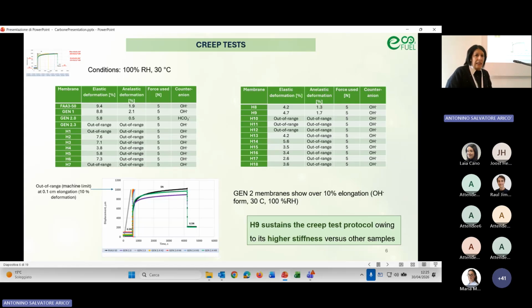The first test in terms of mechanical test was a creep test in the elongation mode. We used the standard protocol that we have set at CNR that consists in stretching the membrane at 0.5 Newton, then a sudden increase to 5 Newton for 1 hour, and again returning to 0.5, and this was set up for the benchmark. The membrane of generation 1 was successful for this test, while of all the other membranes, only the H9 from Gen 2.4 reached the complete test. So we decided that this test was not successful for the selection of this membrane in terms of mechanical properties, because the elongation was higher than the limit of the instrument.